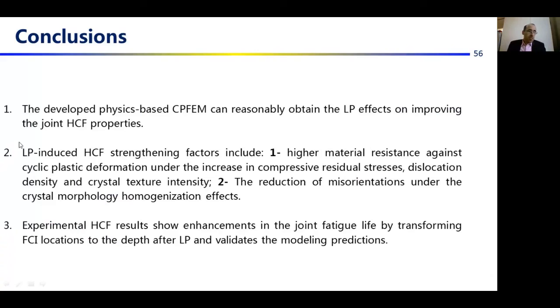joint fatigue properties. Laser peening induced high cycle fatigue strengthening factors include higher material resistance against cyclic plastic deformation under compressive residual stresses, dislocation density and crystal texture intensity, and the reduction of misorientation under the crystal morphology homogenization effect. And experimental high cycle fatigue results show enhancement in joint fatigue life by transforming FCI locations to the depth after laser peening and validate the modeling prediction.